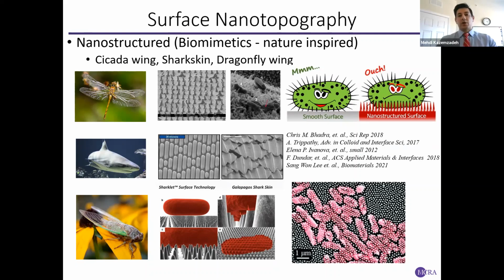For example, shark skin consists of millions of nano ridges arranged in a diamond pattern. This texture enables a process called mechanotransduction, which basically provides mechanical stress on the microorganism. In such an environment, bacteria live no longer than 18 minutes, which is not enough lifetime for reproduction. Some other techniques under development use a magnetic field and low-level electrical stimulation at the implant surface. Also, antimicrobial peptides are novel antimicrobial agents to be used.